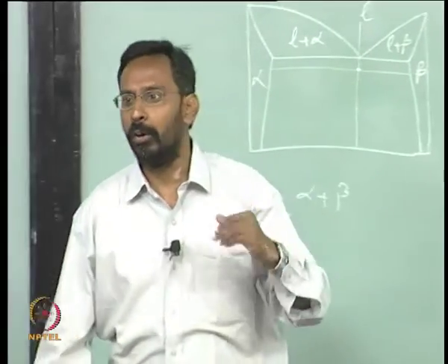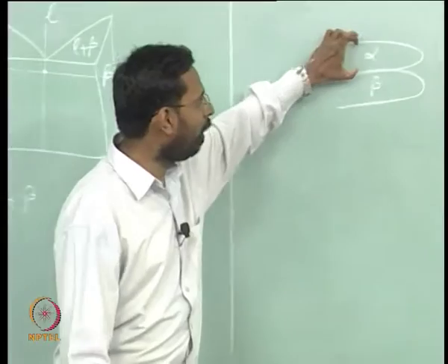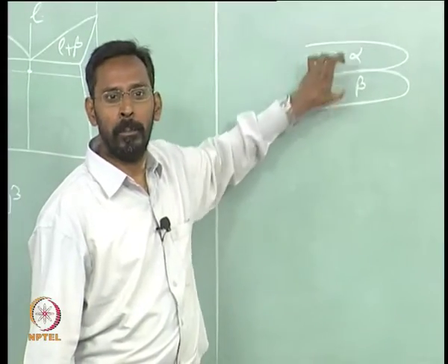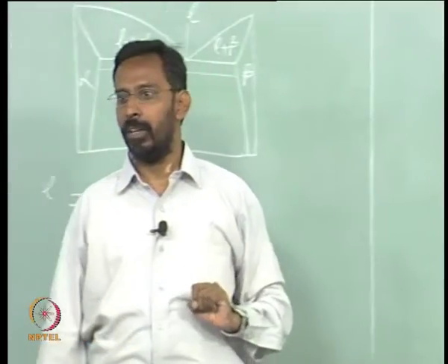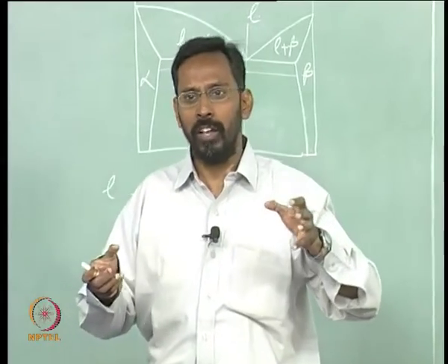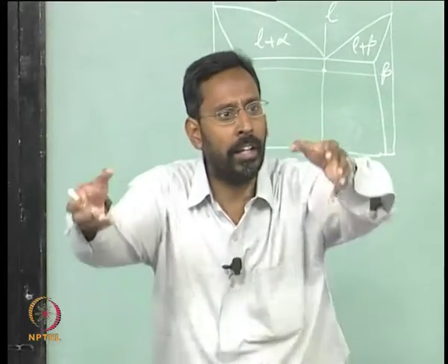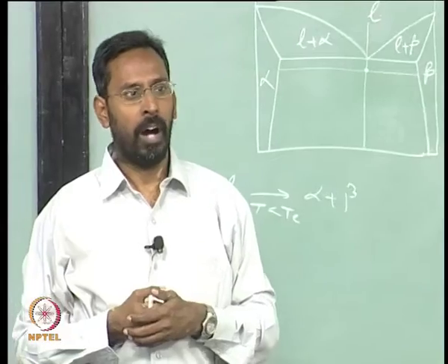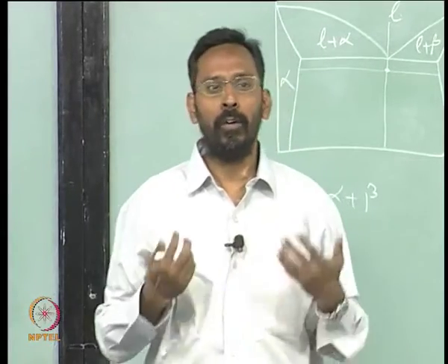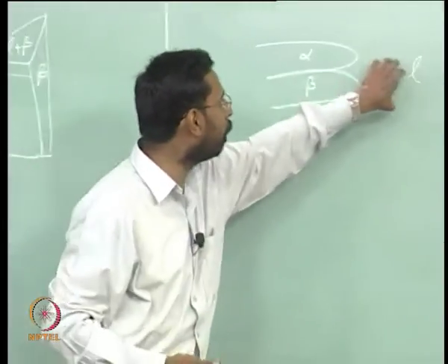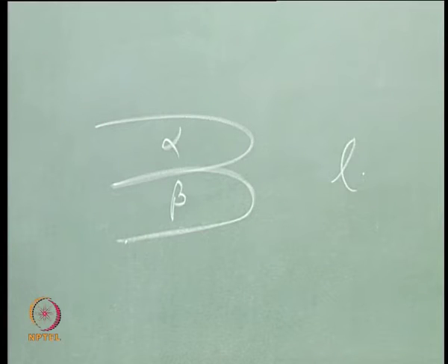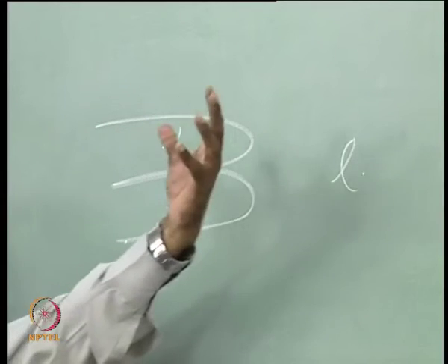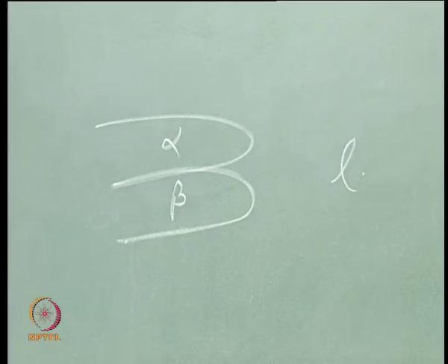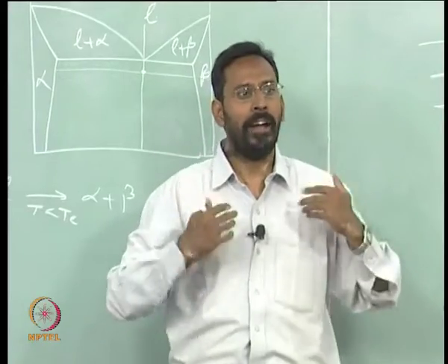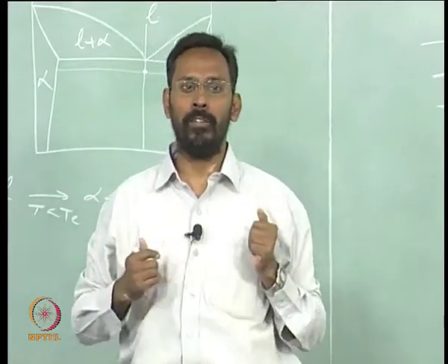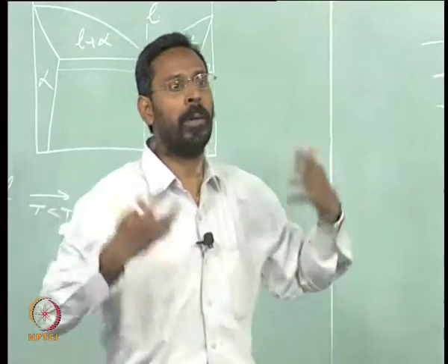If they want to grow, what you see is that alpha is an A rich phase, beta is a B rich phase. So an A rich phase and a B rich phase, both of them are growing together into the liquid. How do these two grow? They can grow only when the liquid supplies atoms to alpha and beta, isn't it? Atoms are actually coming from the liquid to alpha and beta, they are joining alpha and beta, and as a result the alpha and beta are growing together at the expense of the liquid.